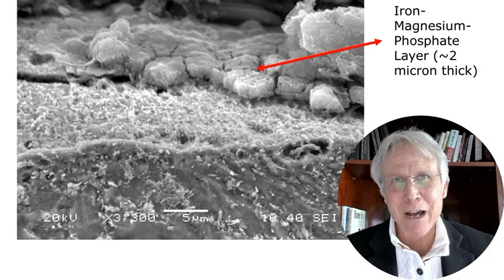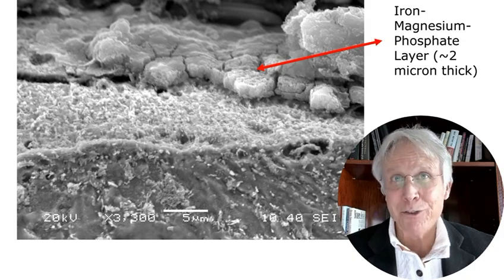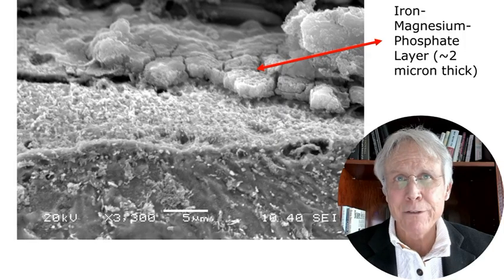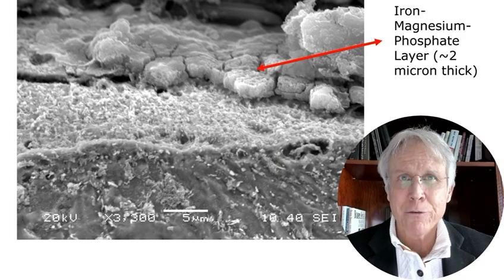This is a very high magnification of the actual alloy layer as it mates with the base metal. We damaged the layer a little in order to show you these photos. Notice that the alloy layer is only a few microns thick, but in the world of corrosion, that is plenty. The protective layer on stainless steel is measured in angstroms. 1 micron is 10,000 angstroms.